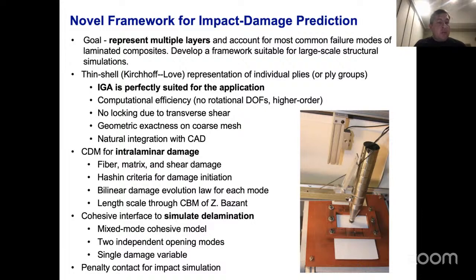For the damage modeling part, we're not doing anything particularly new. We're just using traditional continuum damage mechanics, representing fiber, matrix, and shear damage, Hashin criteria for damage initiation, a bilinear damage evolution law for each mode, and the length scale is brought in through the crack band model of Bažant. To simulate the delamination, we take our Kirchhoff shells, and these deform individually. They don't know anything about each other. And we connect them through cohesive interfaces. But these cohesive interfaces can fail, essentially enabling us to simulate delamination. In particular, we've developed a mixed mode cohesive model where we take two independent opening modes, but a single damage variable representing delamination.